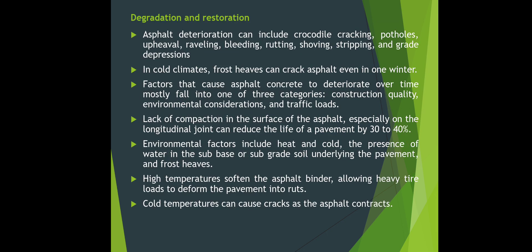Degradation and restoration: asphalt deterioration can include crocodile cracking, potholes, upheaval, raveling, bleeding, rutting, shoving, stripping, and grade depression. In cold climates, frost heaves can crack asphalt even in one winter. Factors that cause asphalt concrete to deteriorate over time mostly fall into three categories: construction quality, environmental considerations, and traffic loads. Lack of compaction in the surface, especially on the longitudinal joint, can reduce the life of a pavement by 30 to 40 percent.